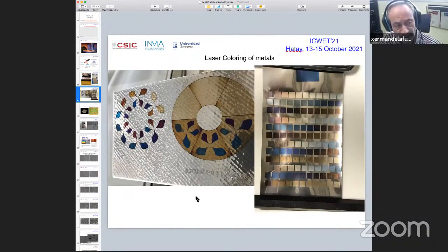And this is a different type of application. This is not cleaning anymore. This is structuring, surface structuring. You can see this is one type of stainless steel. You can see we can get very different colors through oxidation. This is PVD deposited titanium over a ceramic, and it's the same effect. What we're doing here is oxidizing the titanium, and the degree of oxidation, or the layer of oxidation, determines the type of color that we get. You can see very distinct colors here, and also here on the steel. And this is a well-known effect.